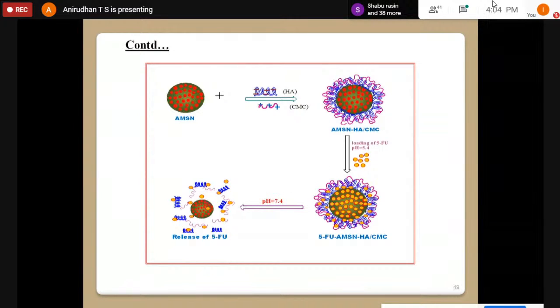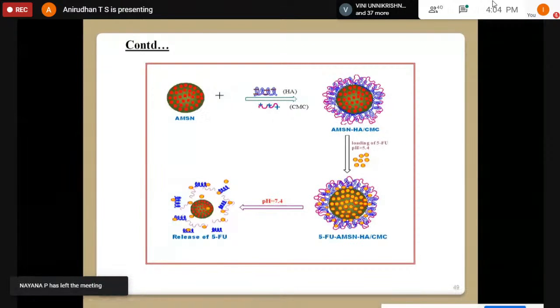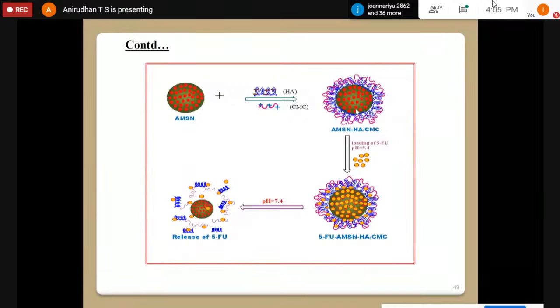So what happens after loading your drug? At pH 7, this structure may be damaged, then your drug may be released, and that particular anti-cancer drug 5-fluorouracil easily leaches out from this drug carrier. So I want to conclude this. What are the advantages of this polyelectrolyte system? In mesoporous silica, you introduce an amino group. This amino group may interact with the carboxylic group of the hyaluronic acid, which then interacts with the aminated group.